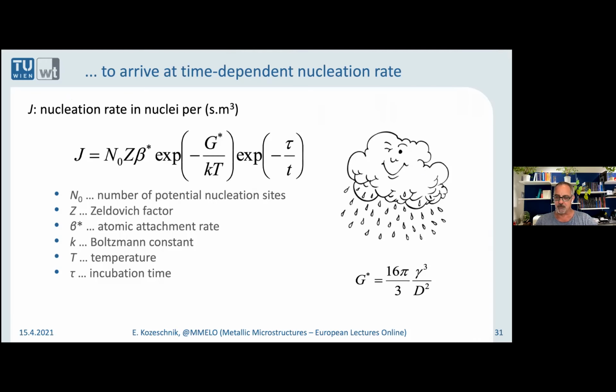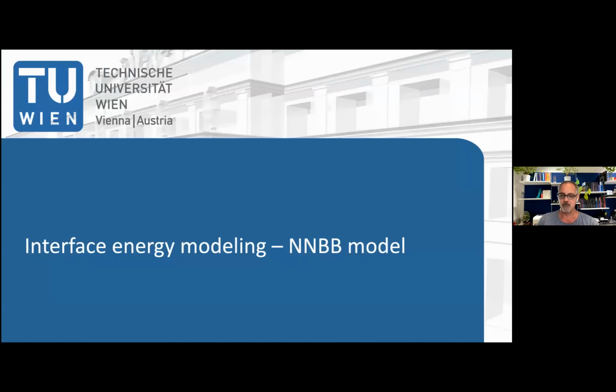To be honest, the first value, the D, which is the effective driving force, I will not discuss, because that is a thermodynamic quantity that you can calculate from computational thermodynamics. Thermo-Calc, MatCalc, Pandat, whatever you have, a Gibbs energy minimizer and a thermodynamic database, you can calculate the chemical driving force. This gamma is the much more interesting part, because that is not so clear yet and not so well established in the community. Gamma is not a fitting quantity, it is a quantity that you can really predict from basics. How can you do that?